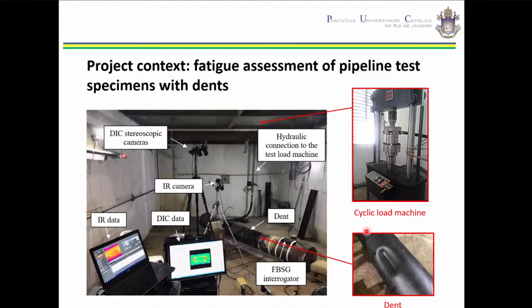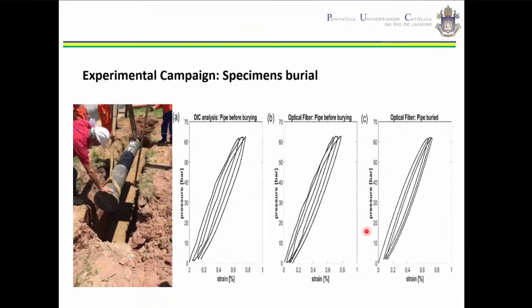After that, we bury the specimens in soil and apply the same pressurization cycles of 60 bars. Here I will only show 3 cycles, but we have done 5 cycles, and compare the results before burying and after burying the pipe with the DIC and the fiber optic strain gauge. As you can see, the levels of strain are very similar, showing that the soil does not offer any benefit, any increase of life, any increase of restriction in the dent area.